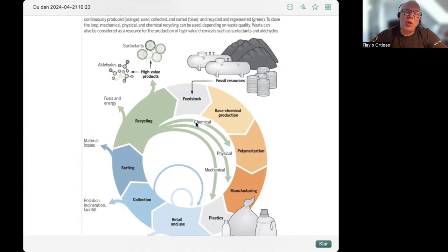The third option is the one of chemical recycling. Well, chemical recycling, there are at least three different technologies. There is solvolysis, which is dissolving the plastics and precipitating it again. This is more in the physical procedure. They have very limited application, but there are two applications that are commonly used, and this is pyrolysis and gasification.